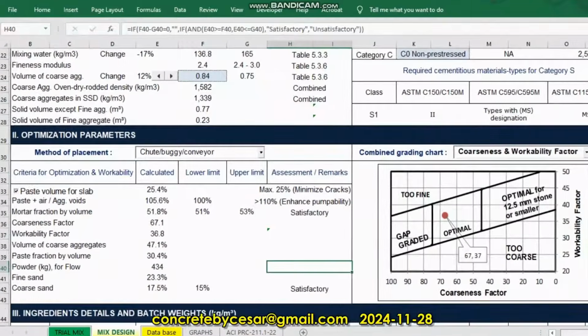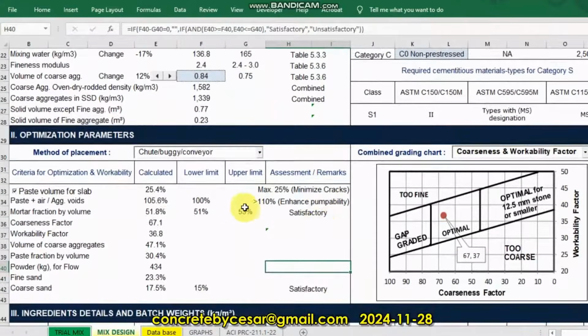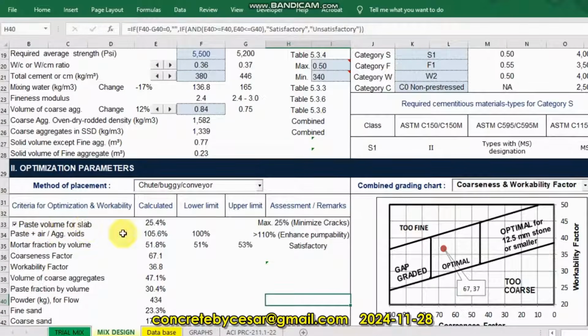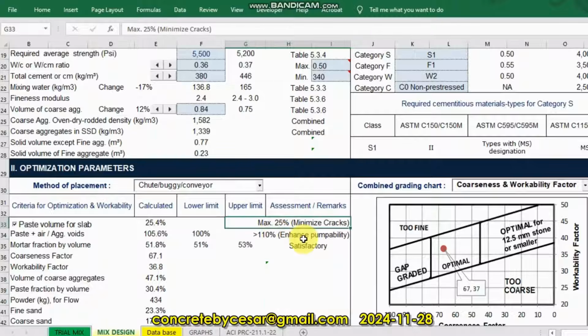For example, our paste volume for slab, since this is pavement, so we consider it as slab. It says maximum 25% of paste volume, so that we can minimize the cracks. Our value is 25.4. We can say it is acceptable. Once you reduce the cement content, then you will see that we are on the safe side with 24.7. That is very easy to analyze when we are using this button. Going back to 380.